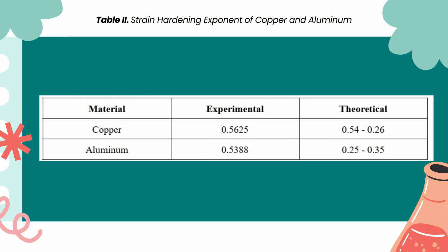For copper, we were very close to the expected range, landing at 0.56. For aluminum, our result of 0.53 was higher than the typical 0.25 to 0.35 range. This discrepancy is actually a great discussion point. It likely stems from the specific alloy compositions of our samples or the initial grain structure of the material before we began testing.